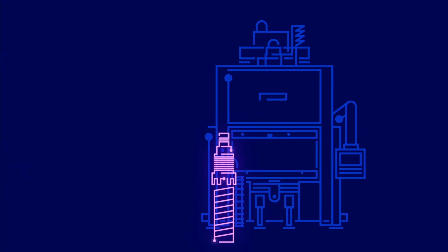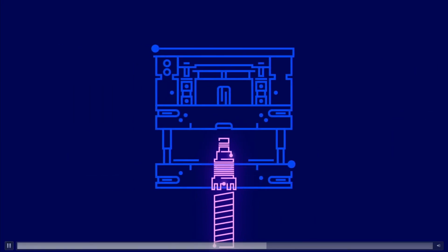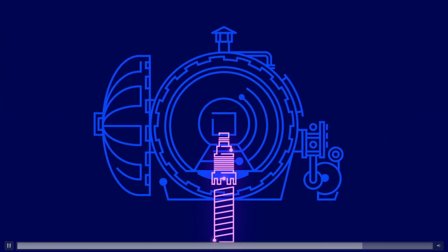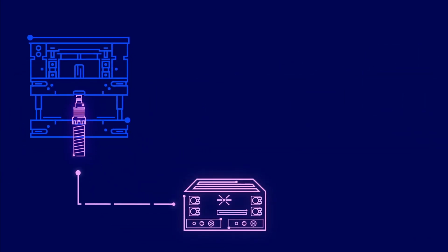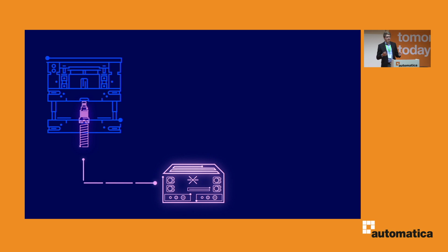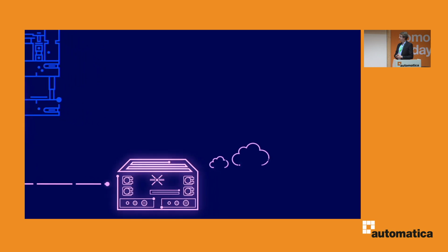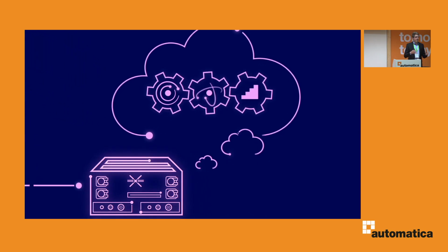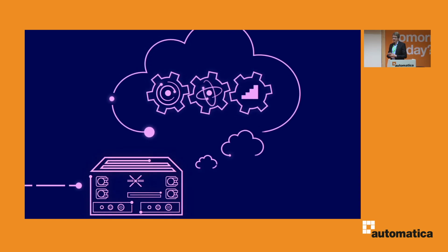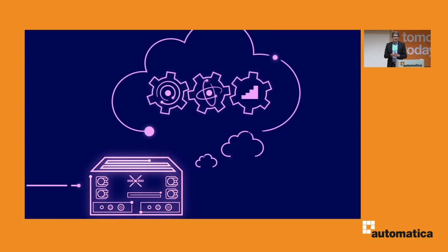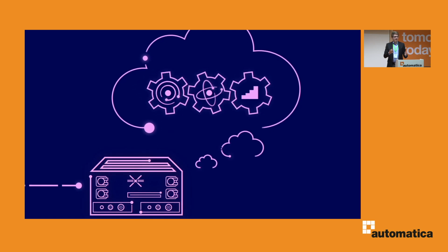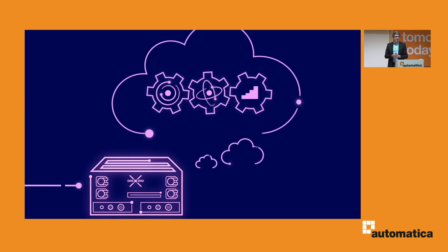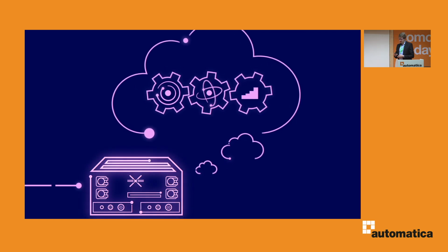So we use dielectric sensors that can be mounted in the plastic production tool, in the mold, and characterize the material while it is taking its shape and hardening. And these sensors are connected to an edge device that is performing the measurements and also collecting data from the machine if it is supplied. And then feeding this data into a machine learning model. This machine learning model allows us to determine if we have reached our quality criteria, for example, a target degree of cure, the target glass transition temperature, and then